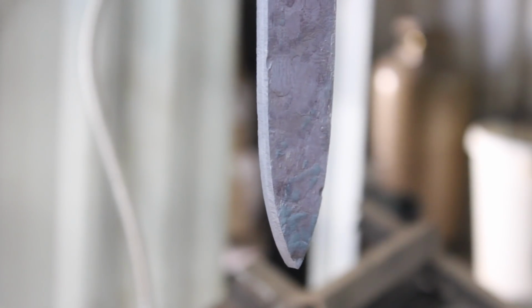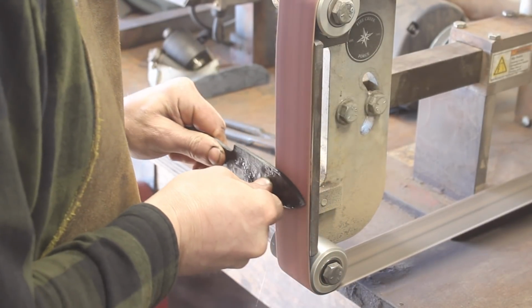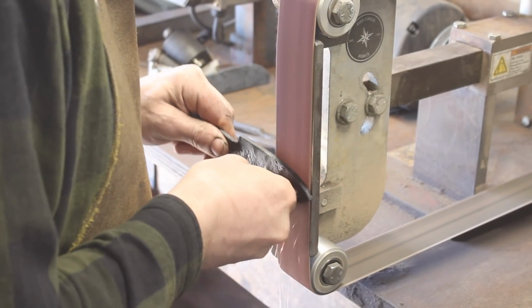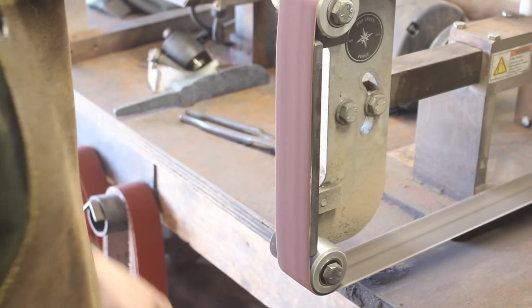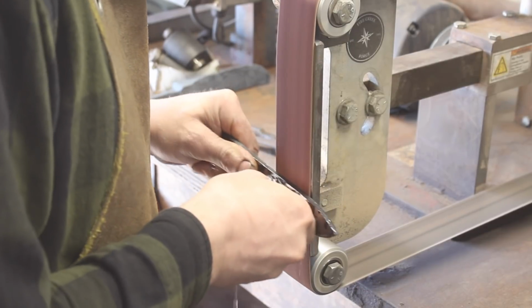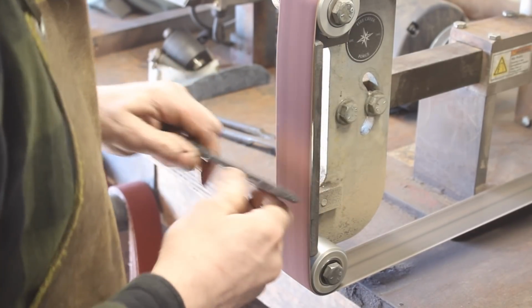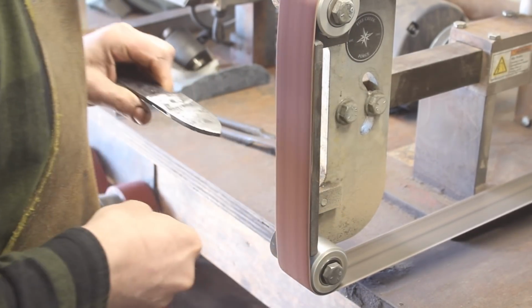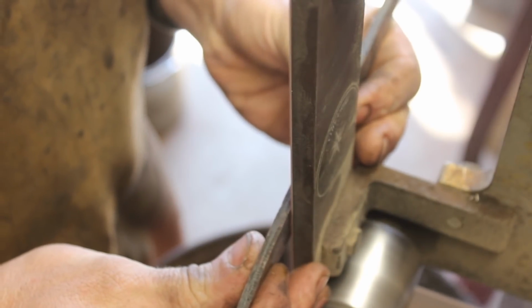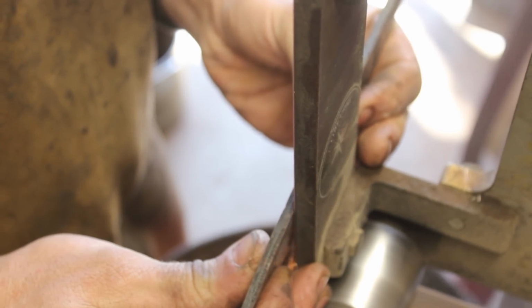Once the thermocycles are all complete, and again, looking at it here, I don't see any irregularities or differences in the cooling rate, which is a telltale sign of an improper or incomplete bond, whether it's a forge weld or a brazing bond, as in this case. Cleaning off the scale here, and we'll go ahead and do a rough grind on this blade.